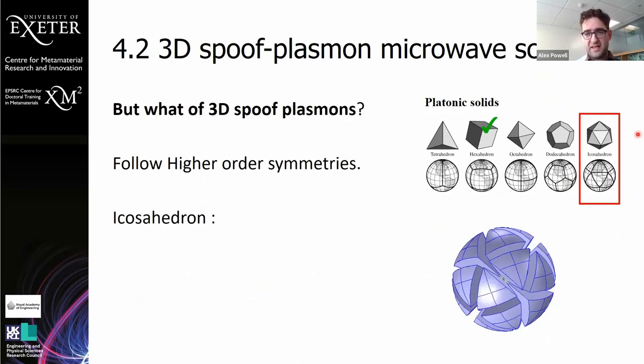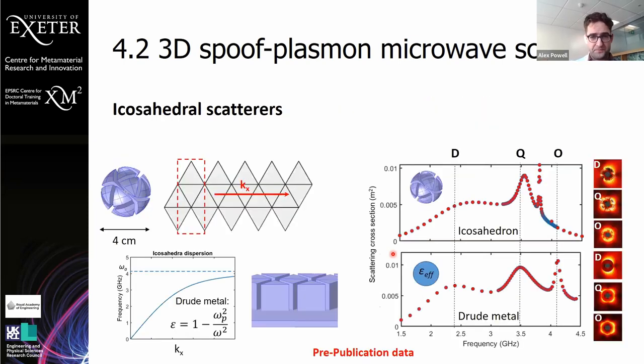And we're going right to the edge, the most high symmetry structures, to look at the icosahedron. So if we make a structure, it's a sphere where we have trenches at every edge of an icosahedron going towards a metallic core at the center. This would hopefully give us more of a surface wave response, the spherical structure. And so the way we look at this is to firstly look at the scattering pattern of the sphere.